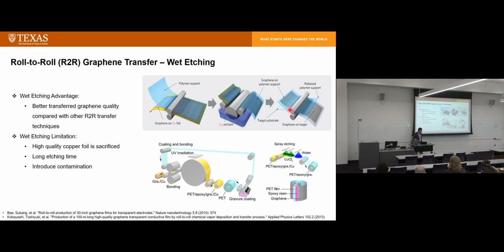Currently, graphene transfer has been using wet transfer, where you use chemicals to dissolve the copper substrate. So you laminate your polymer onto the graphene on copper or other substrate, and then you go through chemical baths, you delaminate, you dissolve the copper, and then the graphene is transferred onto your polymer substrate. Sony has developed this method. The advantage is that there's not much tension involved in the process, so you basically have better quality. There's not much disturbance.